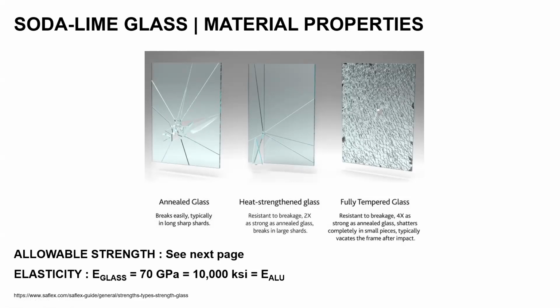The glass we use in architecture is soda-lime glass. It's a very strong material and quite an elastic material. In terms of elasticity, it has the same Young's modulus as aluminum, which means if you want to bend a sheet of aluminum or a sheet of glass at the same thickness, it's going to have the same flexibility. However, it's not ductile like aluminum is. For architecture, it's produced into three types of product: annealed, heat strengthened, and fully tempered.